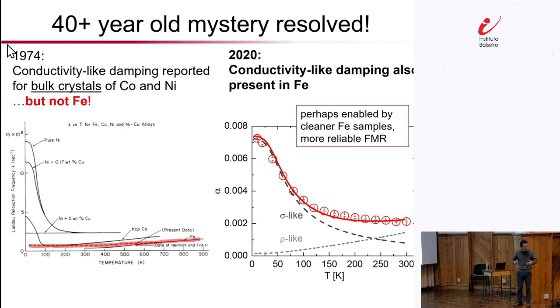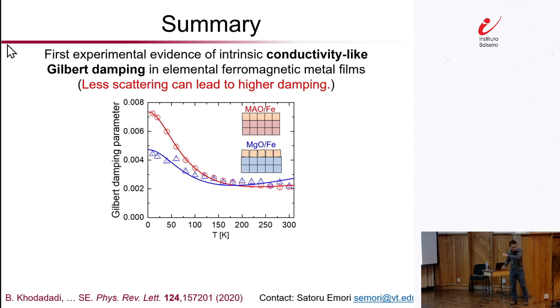Another possibility is a little more technical. It has to do with the complication of analyzing FMR results for large bulk samples, millimeter-thick samples. In such cases, you might have microwave excitation that's not even uniform within the sample, and you might have a huge amount of eddy current damping that's also not necessarily uniform. So it becomes very complicated to extract the true Gilbert damping parameter or Landau relaxation lifetime. So perhaps these people also saw conductivity-like damping, but they might have overdone their analysis to the point that they effectively erased its signature, perhaps attributing it to some other coexisting mechanisms. This is all speculative though, because we don't have a time machine to go back to the 1970s. So I'll stop here with the speculation, and in fact, I will stop here with my talk.